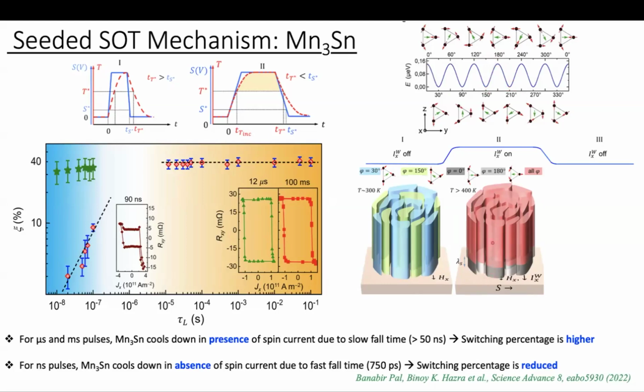So when the writing pulse is off, some small switching happens close to the interface, and it forms a small layer, which we denote as lambda s, and we call it the seed layer. The remaining layer, shown in red color, is where all domain configurations are possible. Now whether the remaining layer can be switched or not depends on how you switch off the write pulse. If you switch off the write pulse slowly, the system will get enough time. Then the entire layer will be switched, and it will relax into 210 or 330.